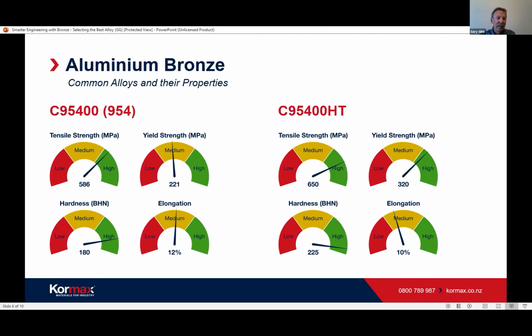Now, one thing about aluminium bronzes, well, not all aluminium bronzes, but certainly ones like 954, is they can be heat treated. As you can see from the graphs there, the heat treatment improves the properties considerably. The tensile strength goes up, the yield strength goes up hugely, and the hardness increases quite significantly. That's becoming more popular with the aluminium bronzes, but there are limitations on the manufacturing process for that, and with the hardness you've got to be very careful, because of the loss of elongation. They tend to be a bit brittle as a trade-off, so you've got to look at the application quite carefully.